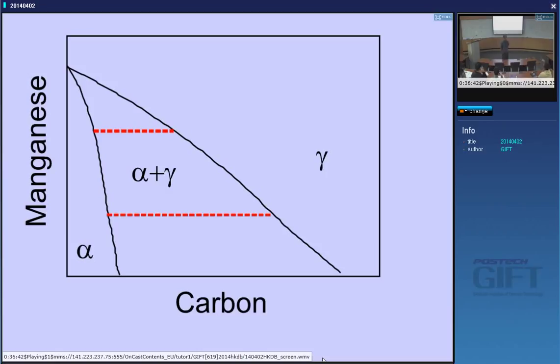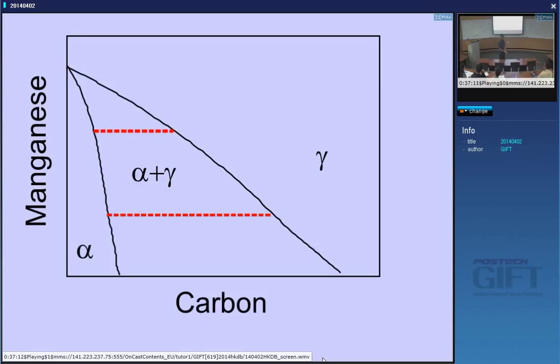The soft interfacial energy prevents the spike from becoming narrower down to lower temperature, meaning the onset of paraequilibrium happens at a lower temperature. As soon as the mobility is lost, you get paraequilibrium. If you go down even further in temperature, you get displacive transformations. So you can see that the manganese is trapped in the ferrite — it doesn't want to be there.